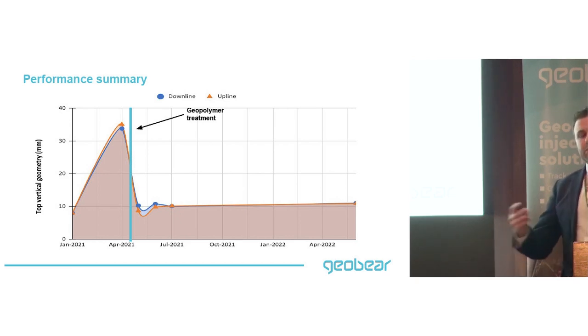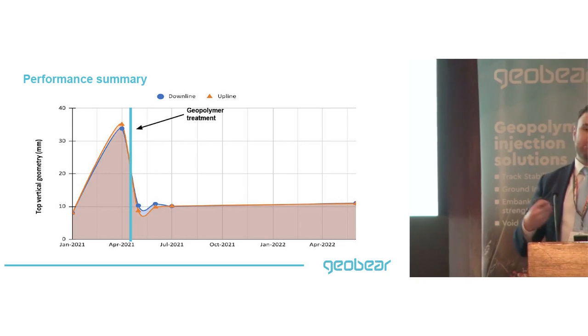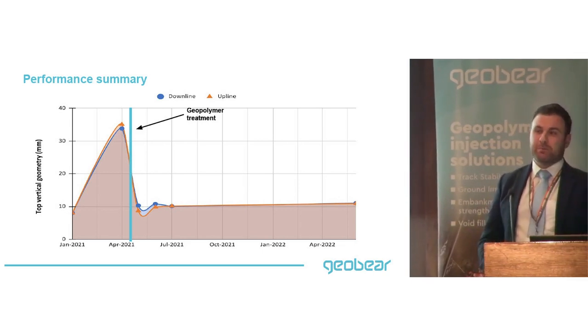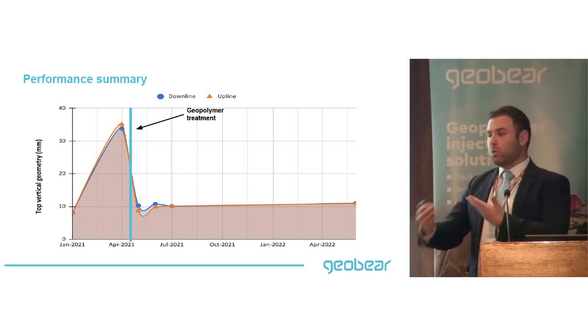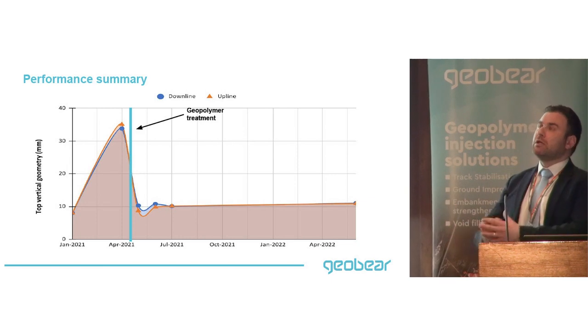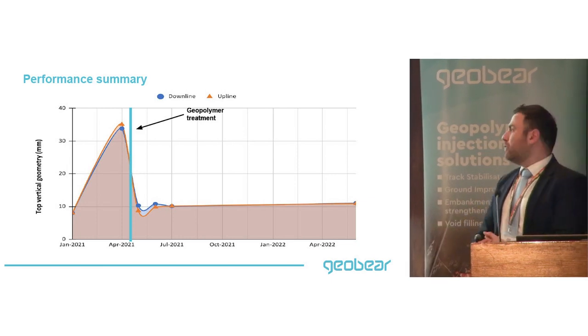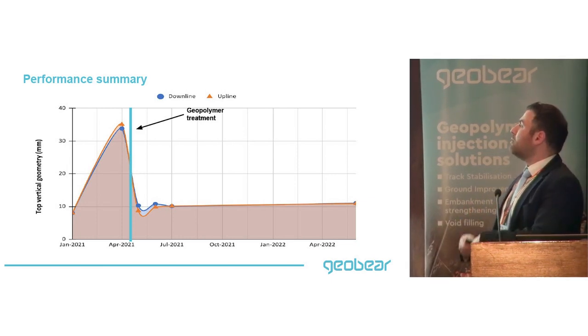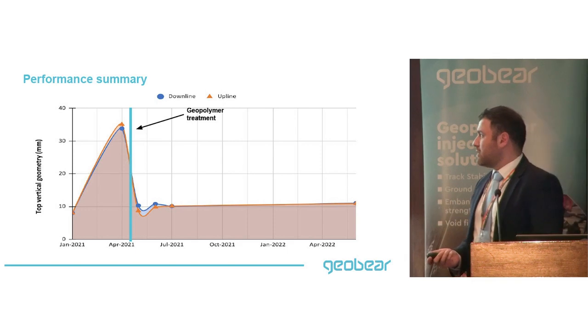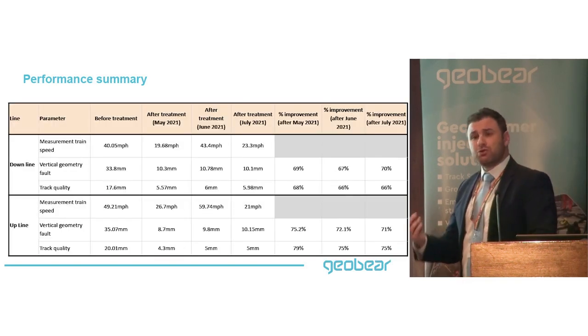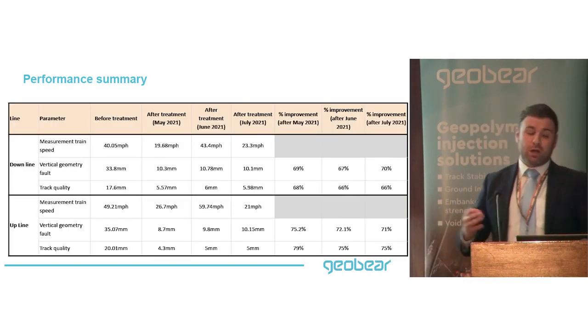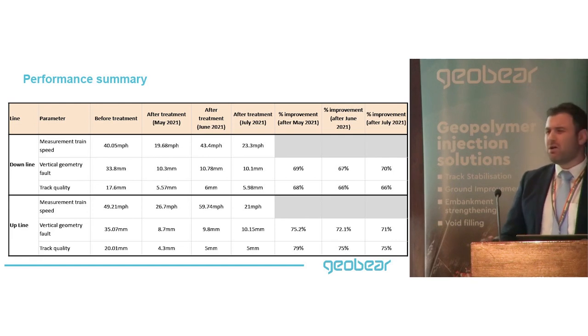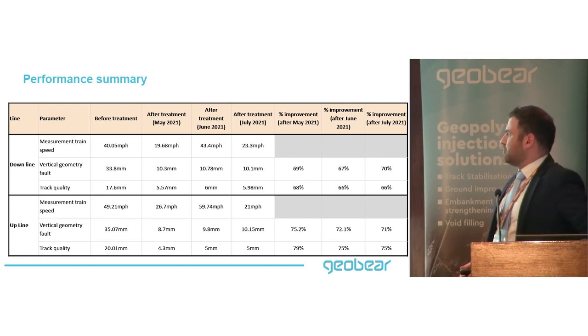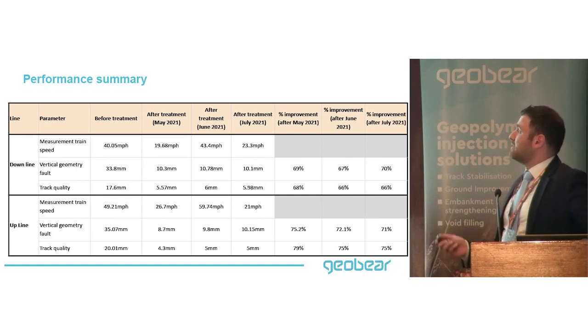This is because when we injected geopolymer in the subbase, we strengthened and compacted the subbase, creating a better platform, which in turn improved the load spreading on the soft soil, and hence reduced the long-term deterioration. We estimate we managed to improve track quality and reduce rate of deterioration by around 70% on average on both up and down line. This is just detailing the values and measurements taken at different speeds and so on.